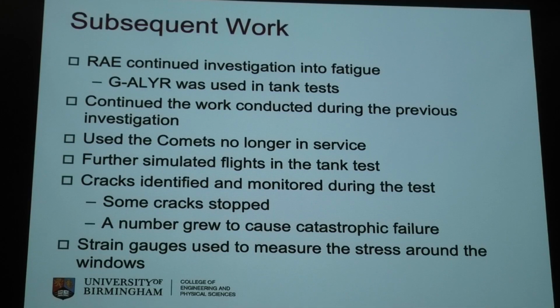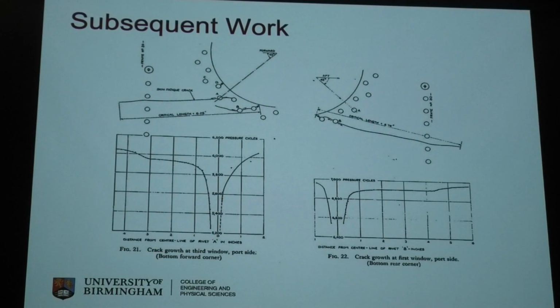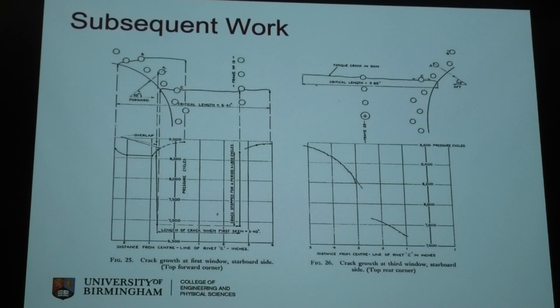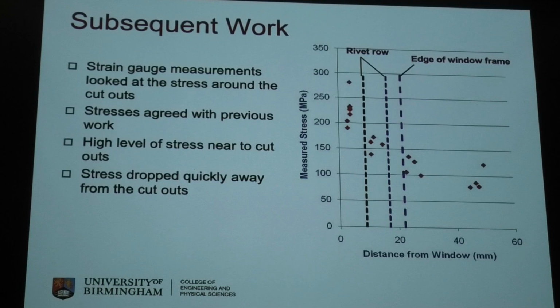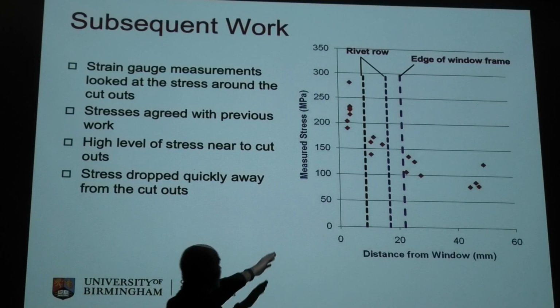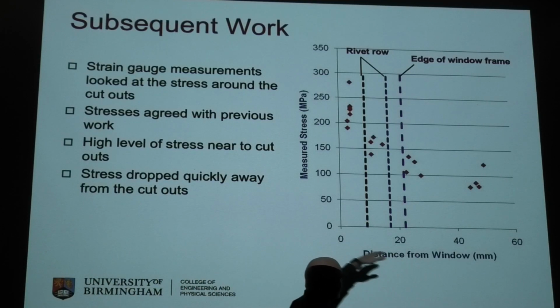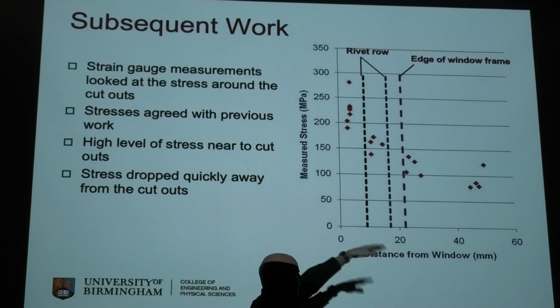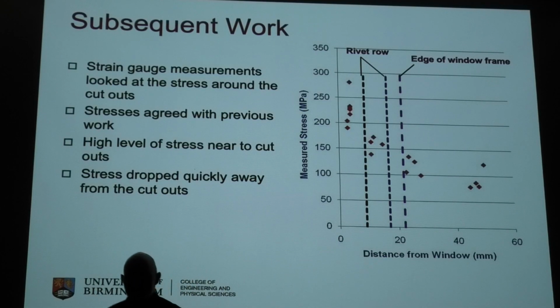And they used strain gauges around the cutout. So they did lots of work to understand what was happening, but not much on the fundamentals. And so you've got pages and pages like this, where cracks have grown and you can see number of cycles versus crack length. Pages and pages of this stuff. And you end up building up this kind of model where you say, well, what's the stress, and where are your strain gauges, and distance out from a window in millimetres against measured stress, and you can plot all this out, and suddenly say, well, you can see where the stress gets quite high, nearly 300 megapascals right by the window, but as you pass through the first and second rivet row, then actually it's going to taper off.